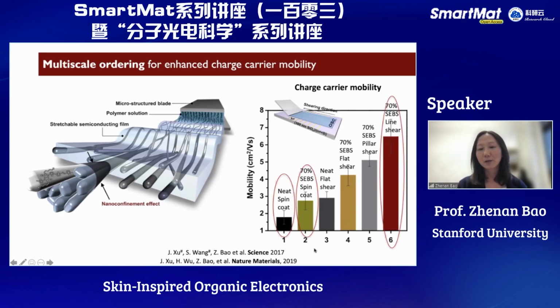But still, to our surprise, we were hoping to just maintain the charge transport and not decrease it. But we found that compared to the neat pure semiconducting film, adding 70% of insulator, we actually saw a boost in the charge carrier mobility. We attribute that to improved nanoscale order, because the pre-aggregation in solution forces the polymer to disentangle and align along the nanofiber. So some of the kinks that may originally exist in the polymer become removed because of this nanostructure formation.